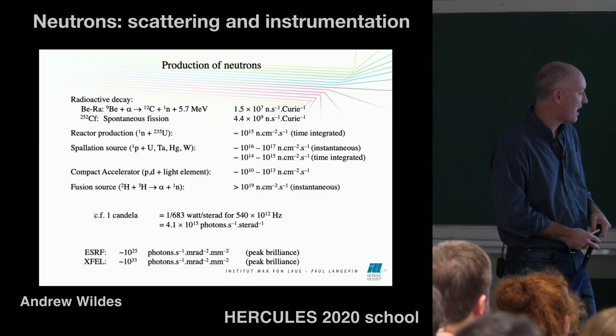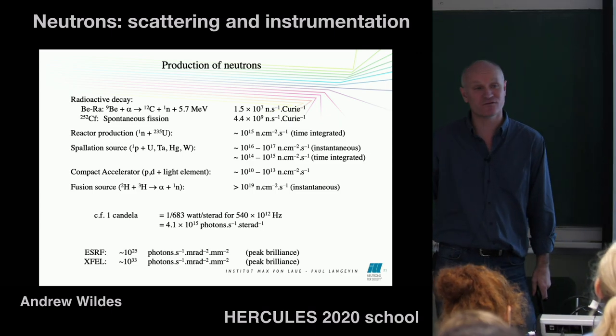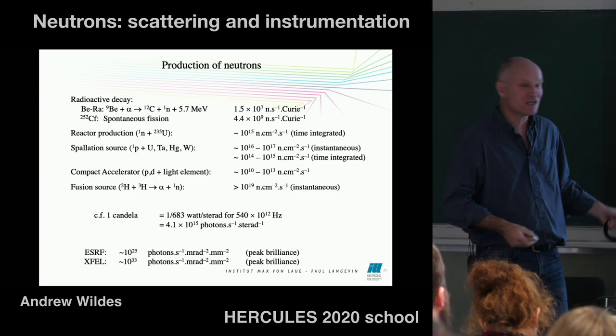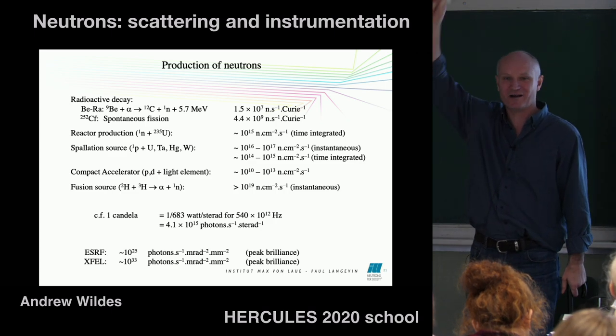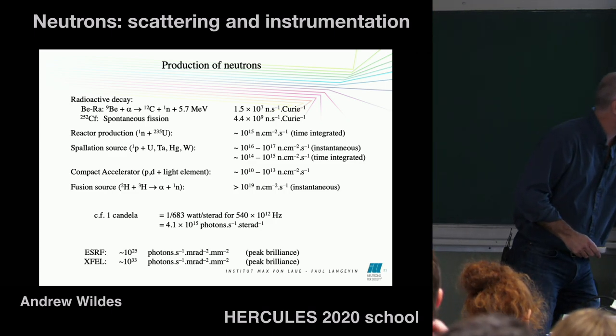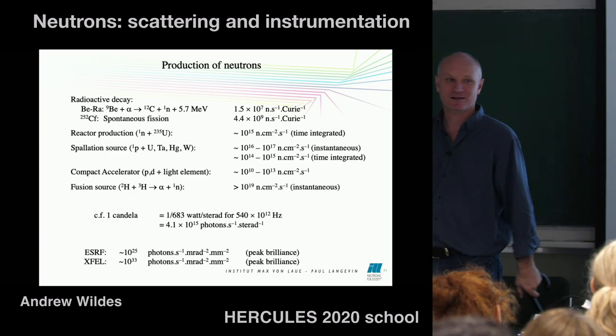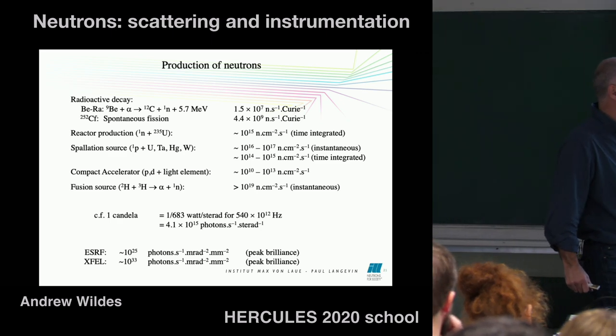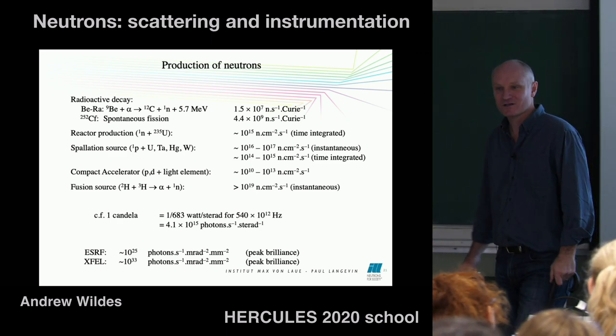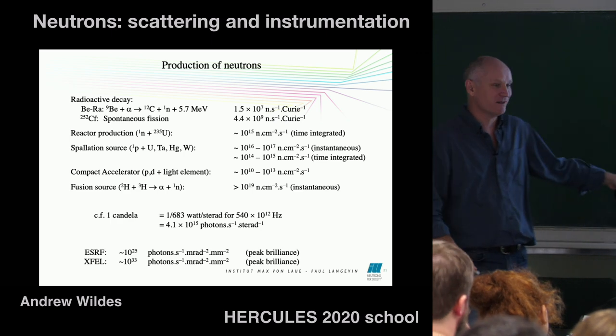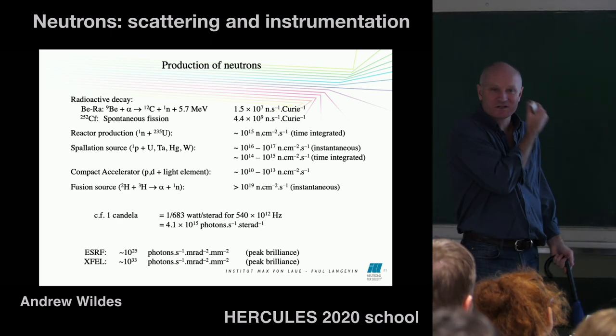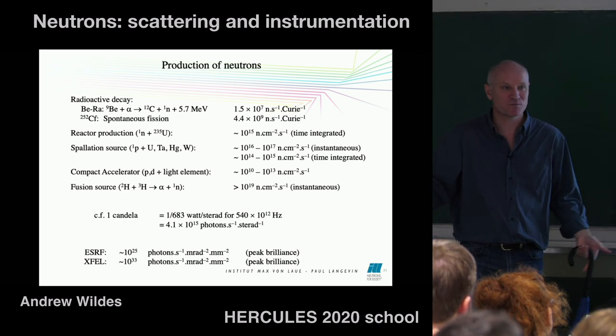10 to the 25 for the ESRF, and probably more now because they've just upgraded the source. XFEL, greater than 10 to the 33. And bear in mind as well, this is per millimeter squared. So this is per centimeter squared, and this is per millimeter squared. So you've got another factor of 100 that goes into that. The number of neutrons that we have to work with is very small compared to that.